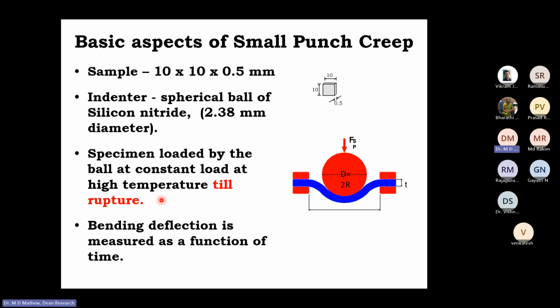So obviously here it is not compression mode of deformation, but what happens to the sample is it is undergoing bending deflection. So instead of measuring depth of penetration as in the case of impression creep, in the case of small punch creep, you are going to measure the bending deflection as a function of time.